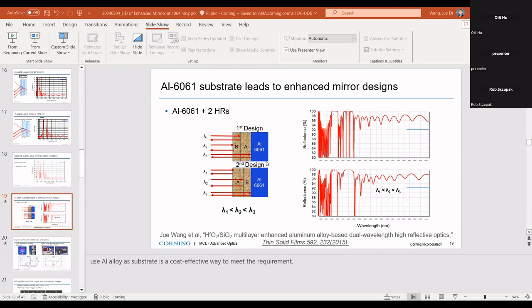Regarding film deposition, we use a plasma source to assist, for hafnia, we use reactive deposition to make a densified coating. We combine two ellipsometers, one from the VUV wavelength region, another for the long wave IR. Based on this, we can generate the optical dispersion for the silica and the hafnia. When we get the dispersion, then we can design different mirrors and optimize the process, right?